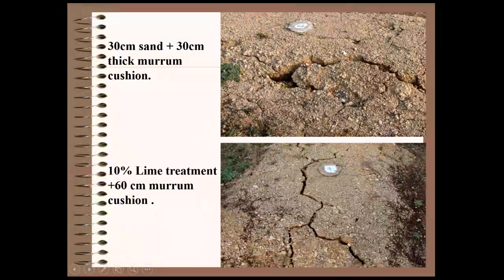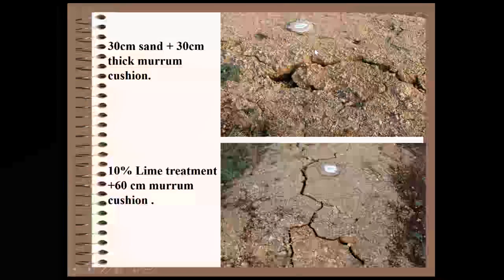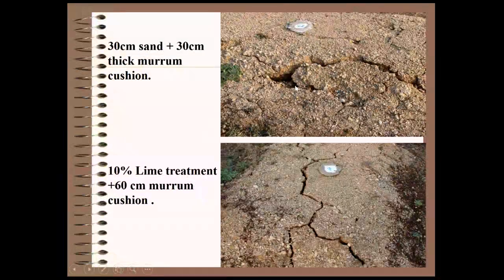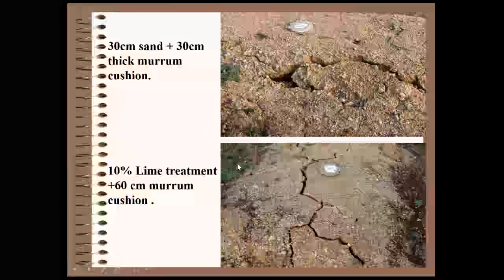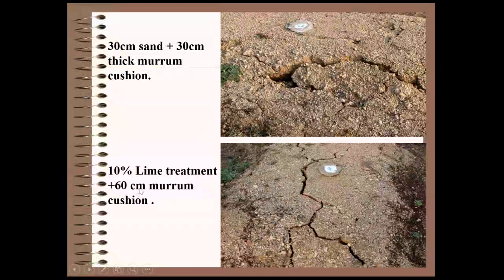During the drying or desiccation under sun, the soil subgrade will be subjected to tensile stresses in the order of 100 to 150 ton per meter square. It's not small. What is this poor soil? Its tensile strength is insignificant. That is why it will break in case desiccation happens in the subgrade. Here 10% lime we have mixed with the native soil, recompacted, and then a 60 centimeter thick morum soil cushion is placed. Even then the system is cracked.